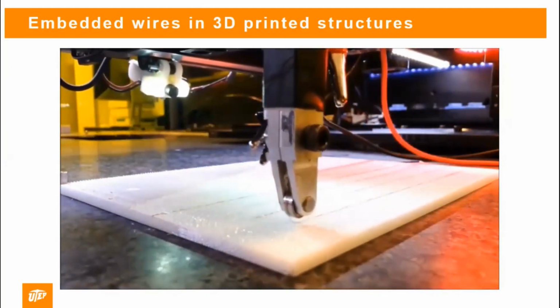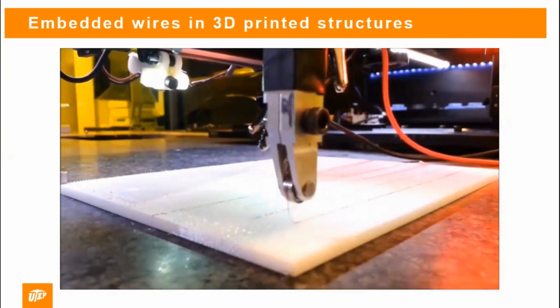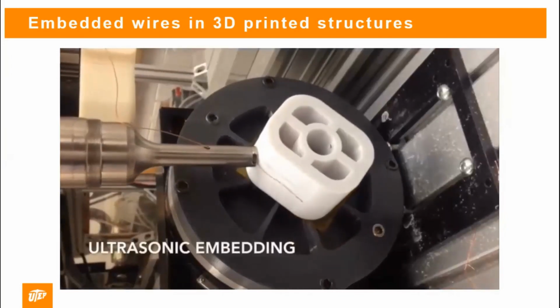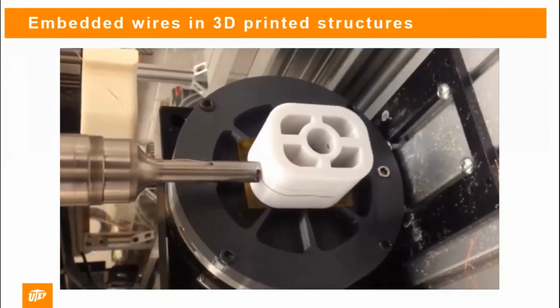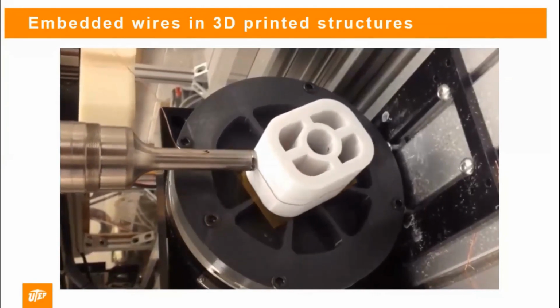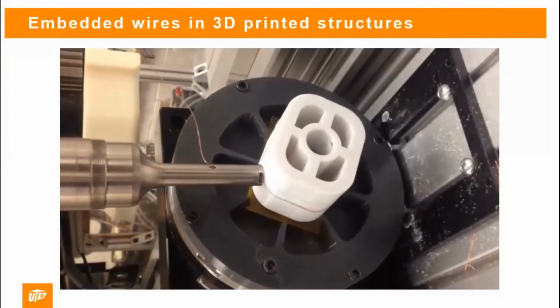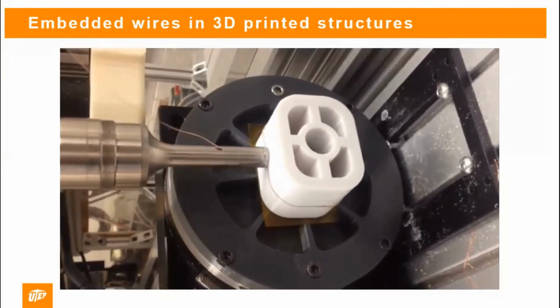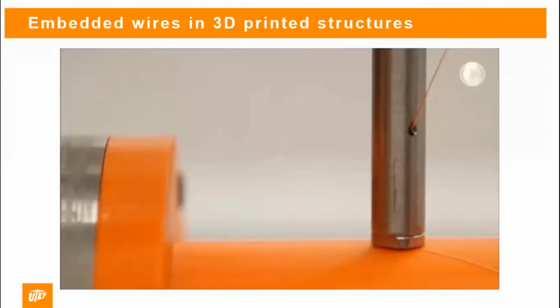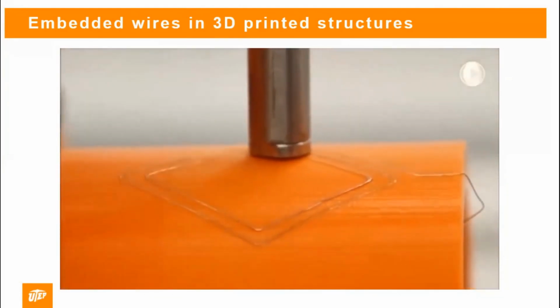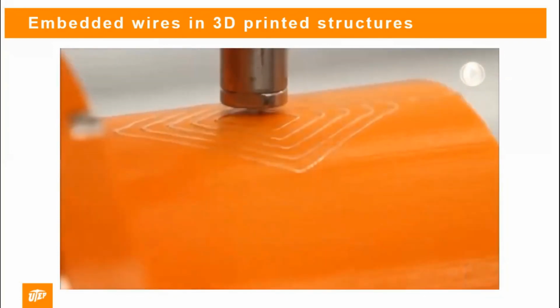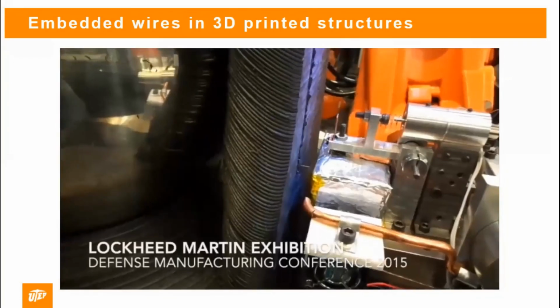Through ohmic heating, we're heating up the wire, putting some pressure. This is ultrasonic. You see the wire going into this little hole, and it's being vibrated to locally heat it, and it just sinks into the plastic. This is actually a singly curved surface. That's an antenna. It doesn't look like it's submerged, but it is.